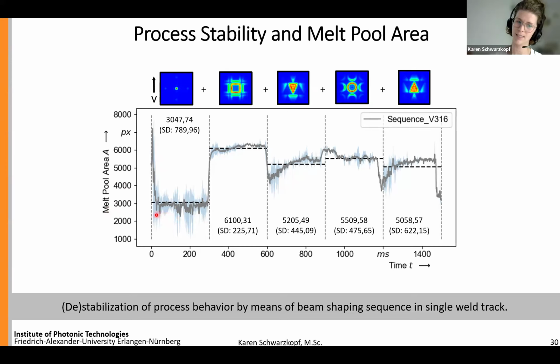And I think what is quite clear is that the point, since we had a reduced beam shape diameter, also results in the smallest melt pool area. But what is interesting to see is that for the more complex beam shapes, we do see differences. And these differences do not only rely on the melt pool area, but also on the stability, which is indicated by these blue transparent lines, which are basically the standard deviation for the 3 repetitions.